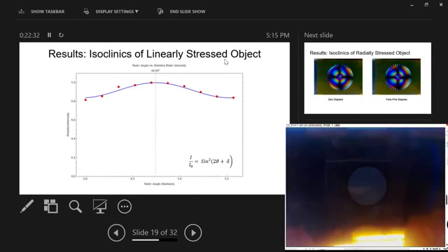And we also, because that one was only considering the angle with respect to the analyzer, so it had a 180 degrees periodicity, we also doubled the angle in our sine squared, which gave us the 90-degree periodicity we were expecting. And I introduced this delta, this phase factor, that allows us to account for where the center of our intensity profile should be, because we're not starting in line with anything. And so doing this, we can see we actually had a pretty good fit with our model.